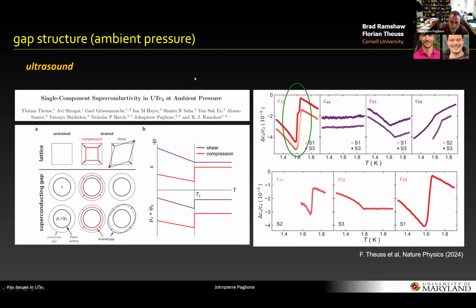We did a really nice experiment with Brad Ramshaw's group at Cornell to study the ultrasound evolution through TC. And we did a very careful study of different samples, in particular, samples that showed a single superconducting transition and samples that showed a double superconducting transition. And the great work by Florian and company, they were actually able to measure this double transition with ultrasound. So this is C33 going through TC, and you can see in sample S3 that there's this jog here. And that's consistent with the heat capacity data.